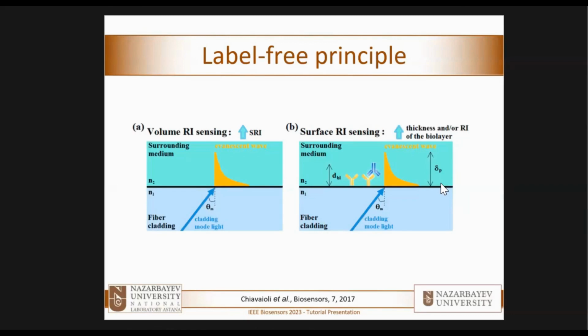It's also important that the skin depth of the medium, so how much the waves penetrate the medium, is quite large. That means we don't see the reflection coming from the immediate surrounding of the medium. That, for example, prevents us from detecting cells with this method, because if a cell is immobilized in the surrounding, as the cell is quite large and has a much more irregular shape, the optical waves will rebound in the cell multiple times rather than just being reflected on the surface.